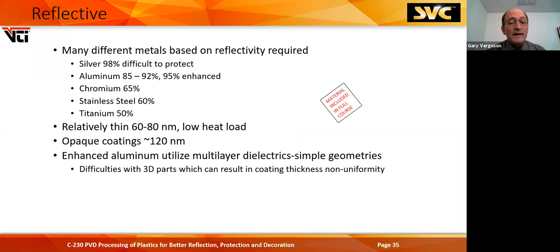Production aluminum is 85-92% reflective, depending on how far you pump down, getting rid of those contaminants in the system. You can bump that up to 95% if you're doing enhanced aluminum with dielectric stacks on it. Chromium comes in around 65% reflective, stainless steel 60, titanium 50.